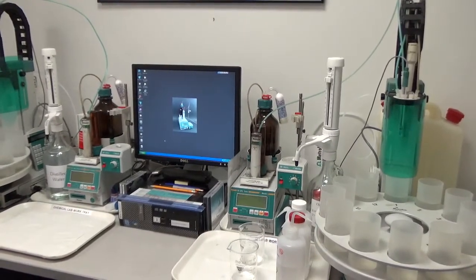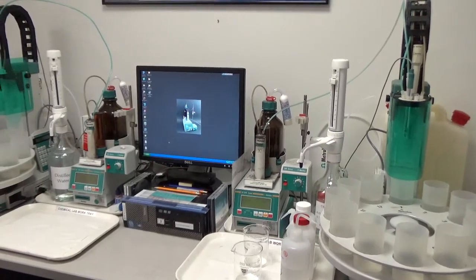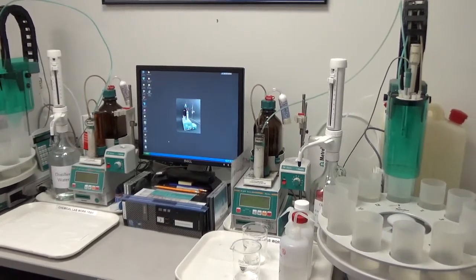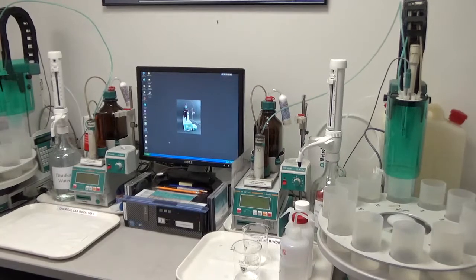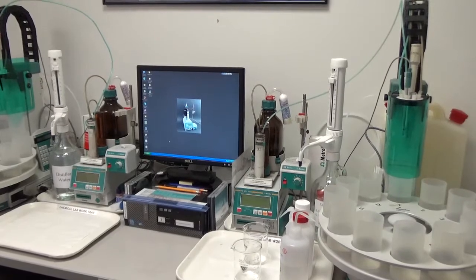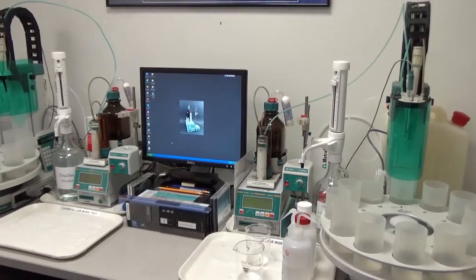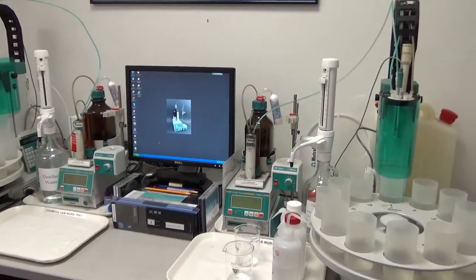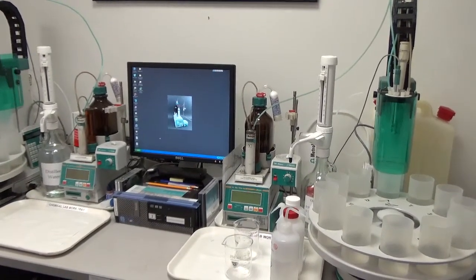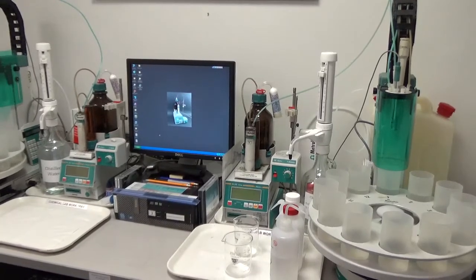When we do water-soluble chloride analysis, we take the same 10 grams of concrete powder and digest it in distilled or deionized water. After we digest in the water, we do the filtration. We filter the solid residues out. We take the filtrate and analyze it for chloride by potentiometric titration with the same silver nitrate as the titrant. So here we have two setups to show you how we do the chloride content analysis on the filtrate after digesting the concrete in acid or water for acid soluble or water soluble chloride content analysis.